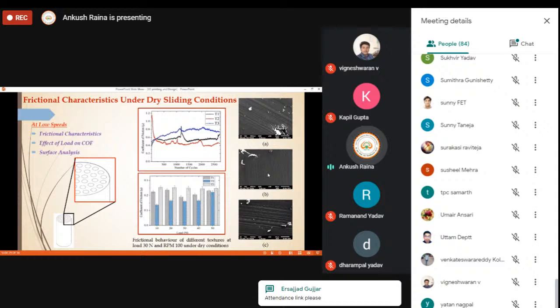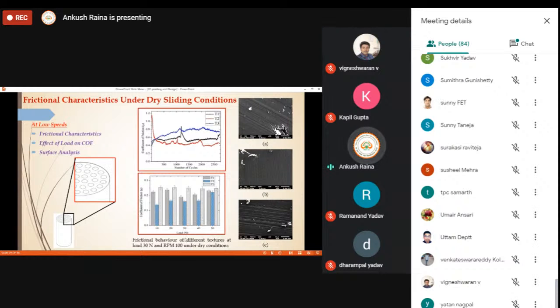If you take into consideration the SEM analysis in all three cases, again at this load, this curve corresponds to this one, this second curve corresponds to this one, and this one corresponds to this one. Here you can also see that for texture T1, there are again some parallel grooves. Parallel grooves mean that there is some kind of abrasion, some kind of material removal, and some plastic deformation can also be seen over here. The surface is not smooth in comparison to this one, which is for texture T2. The surface is smooth over here, and certainly for texture T3, again the surface is not smooth. So it certainly indicates that there is less resistance during sliding in the tribological testing. This texture T2 has resulted in good properties, or minimum frictional properties, in comparison to texture T1 and texture T3.